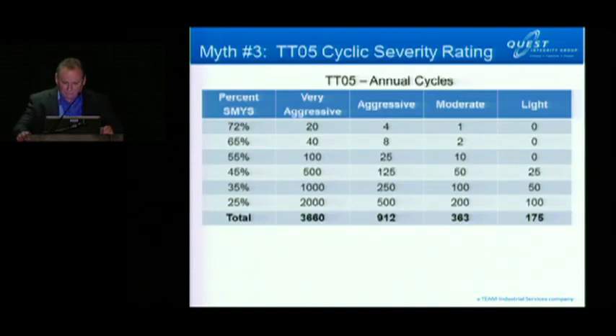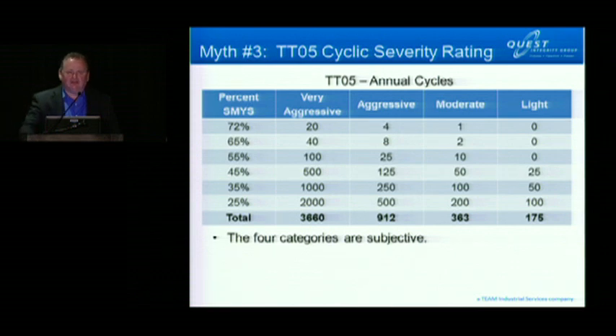And then the final one is what's now in the TT05 document on rating severity of pressure cycling. So you not only have to predict failure, but you also have to predict fatigue crack growth due to pressure cycling. And TT05 has 4 categories of rating pressure cycling: light, moderate, aggressive, and very aggressive. And this lists the assumed pressure cycles that are representative of those 4 different severity ratings. Well, there's a couple of issues that I have with this, one of which is the categories are subjective, which, okay, most rules-based approaches do have some degree of subjectivity in them, so you can forgive it for that.